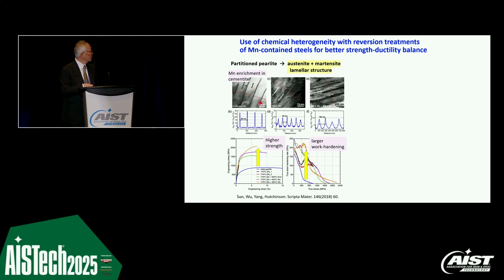This is an example by the Monash people, and they started from partitioned pearlite, in a medium manganese steel, I think. We have manganese enrichment in cementite. After a complete reversion in a short time, we can have an austenite and martensite lamellar structure. By having such a microstructure, they succeeded in obtaining higher strength without losing much in ductility, and also large work hardening.